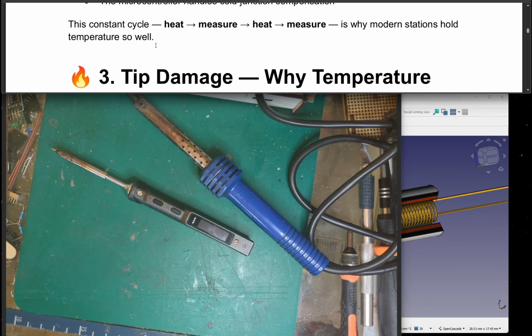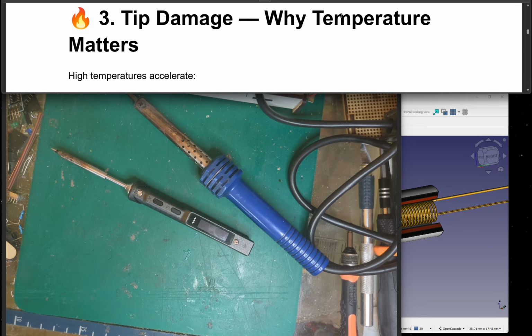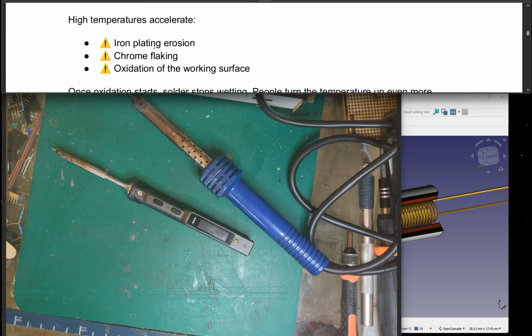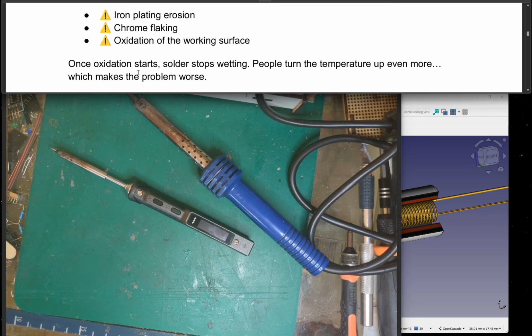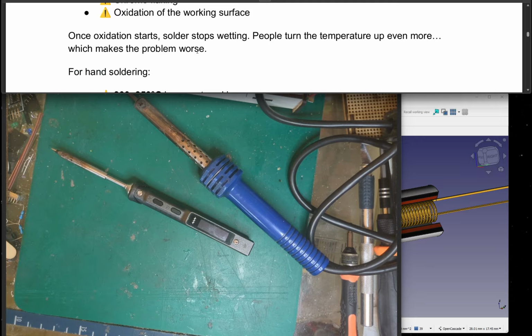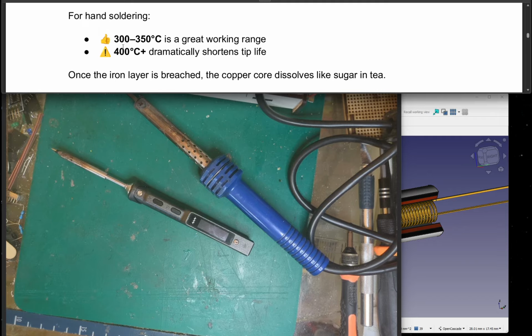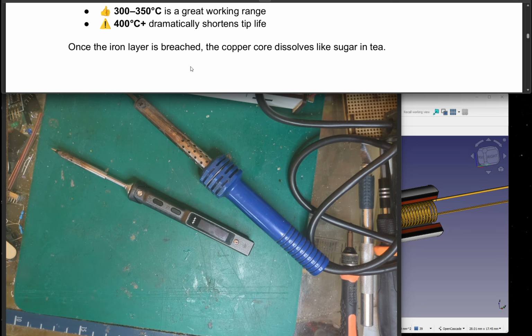So, tip damage. Why temperature matters: high temperatures accelerate iron plating erosion, chrome flaking, and oxidation of the working surface. Once it starts, it stops wetting. People turn the temperature up, thinking it will help, which makes the problem even worse. For hand soldering, between 300 and 350 is a great working range. Over 400 plus, it shortens the tip life. Once the iron layer is breached, the copper core dissolves like sugar in tea. There we go.